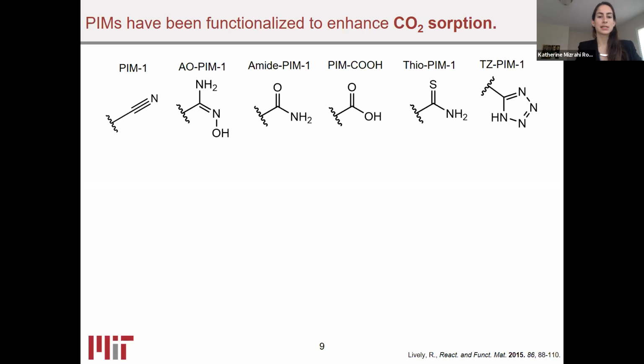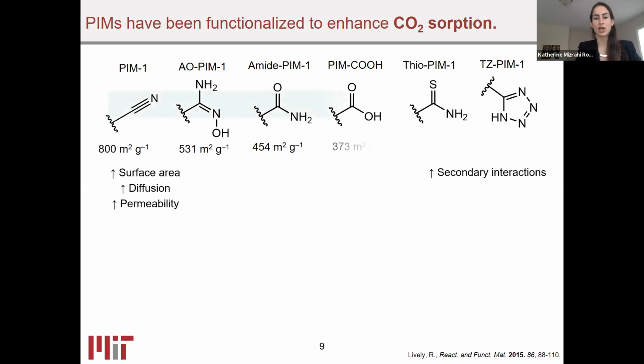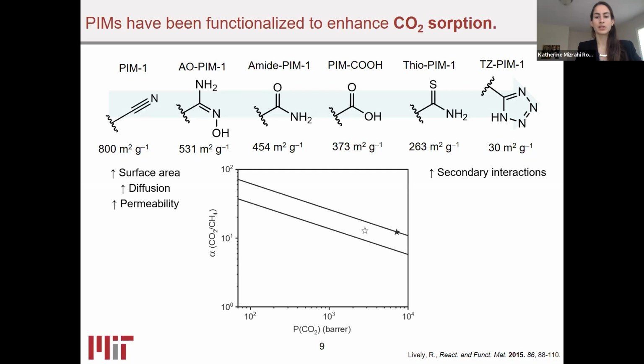One thing that's important to consider here is that as these functional groups are added to the PIM, there can be an increase in secondary interaction, which actually leads to reductions in surface area and, many times, reductions in performance compared to the original PIM1 backbone structure and polymer. So here we actually have the original performance for a PIM1 sample.